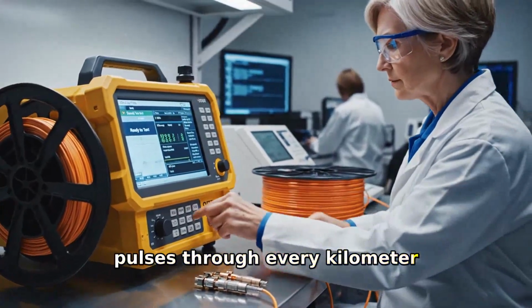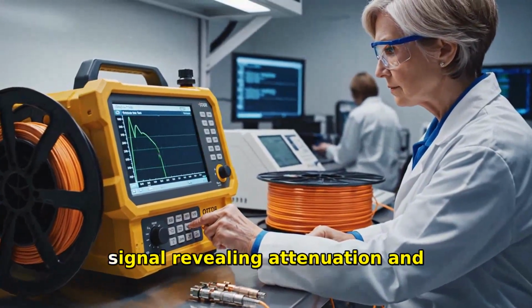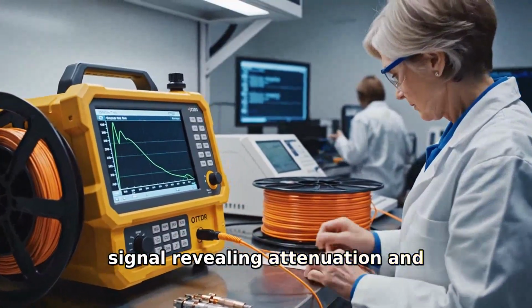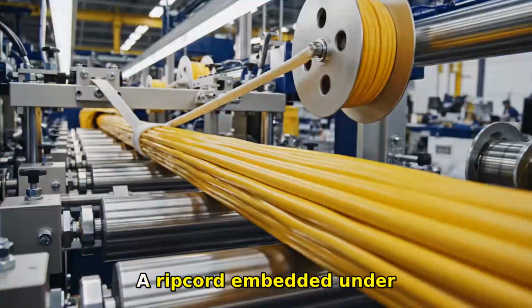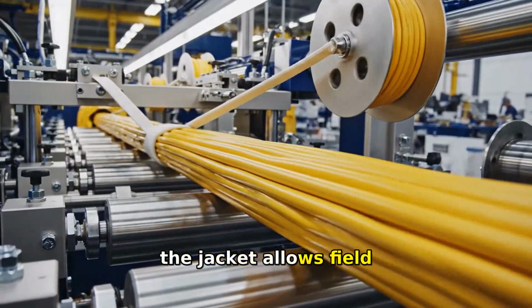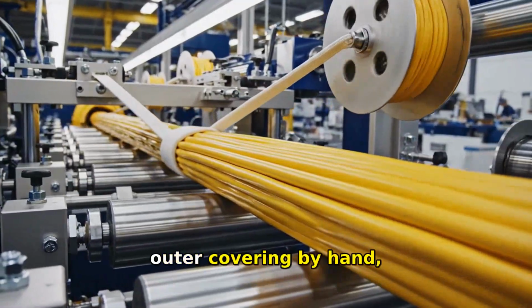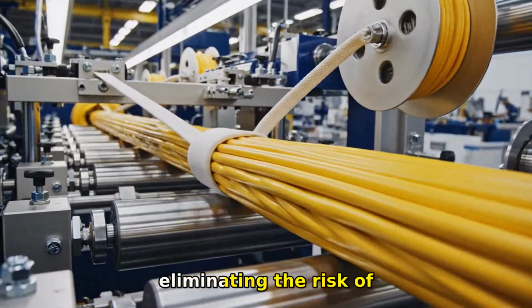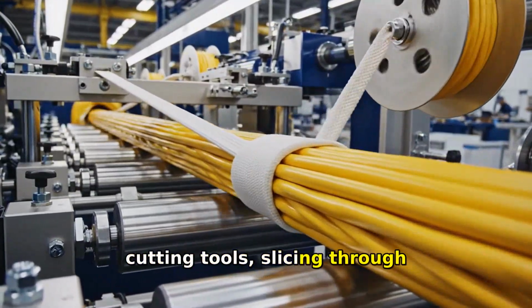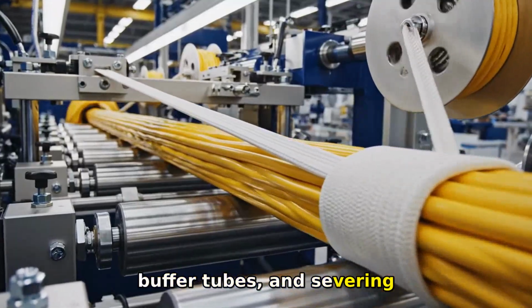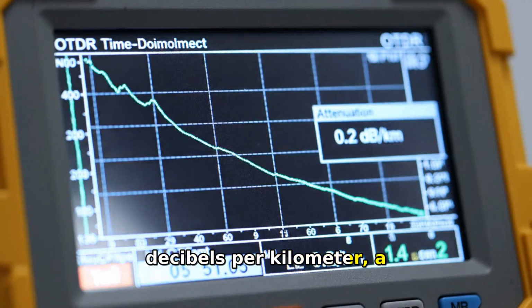OTDR testing fires laser pulses through every kilometer of fiber, the reflected signal revealing attenuation and defects along the entire length. A ripcord embedded under the jacket allows field technicians to strip the outer covering by hand, eliminating the risk of cutting tools, slicing through buffer tubes, and severing fibers during installation. Premium single-mode fiber achieves below 0.2 decibels per kilometer, a signal traveling over 100 kilometers before needing amplification.